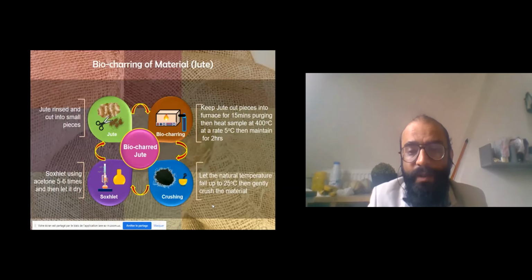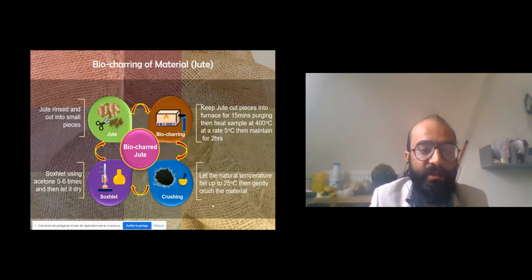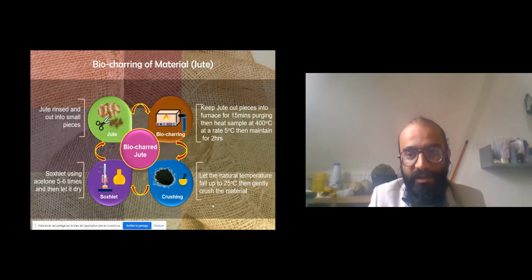Let me show you how we are going to make jute a sustainable material, and how you perform the biochar of jute. Take jute, cut it in small pieces, and perform the biochar in an inert atmosphere. You start purging for 15 minutes, then heat at the rate of 5 degrees centigrade per minute, increase up to 400 degrees centigrade, and hold this temperature for 2 hours under continuous flow, and then you cool it. Till 25 degrees centigrade you provide the inert atmosphere, then you can take it out.